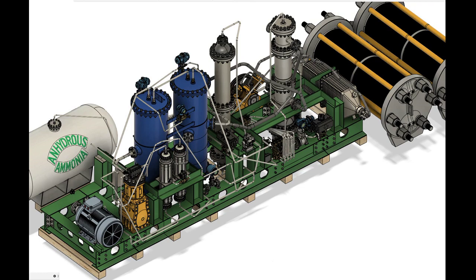Thermodynamics and kinetics. Using high-activity wüstite catalysts at a space velocity of 30,000 per hour at 30 megapascals, the conversion per pass is as high as 30%, requiring a total of 1 kilowatt per kilogram to reheat the gas upon cooling and separation, a total of 3.3 times to achieve full conversion.